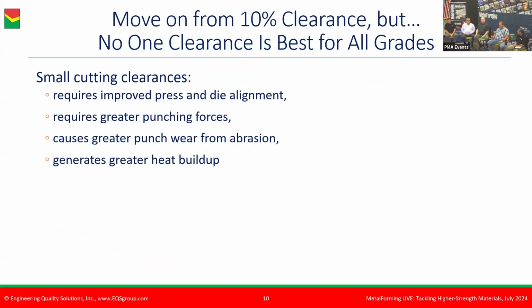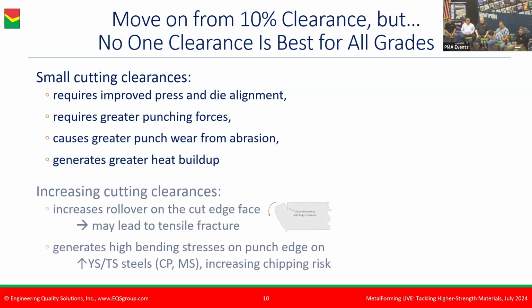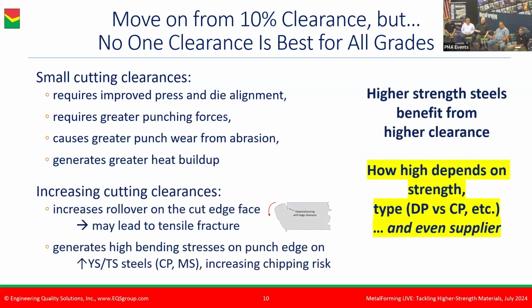Art also alluded to clearances, that 10% paradigm that we grew up with. Well, that probably worked well, and it did work well for mild steels. We've got decades of evidence to show that, but that's not necessarily the case as we go to higher strength products. For higher strength steels, we know we should be increasing that clearance above 10%. However, how high that clearance is going to be is a function not just of the strength level of the material that we're working with, but also the type, be it a dual phase steel or a complex phase steel, that are going to behave differently in your process. And in addition to that, it's going to be a function of the supplier who's providing that particular advanced high strength steel to you.